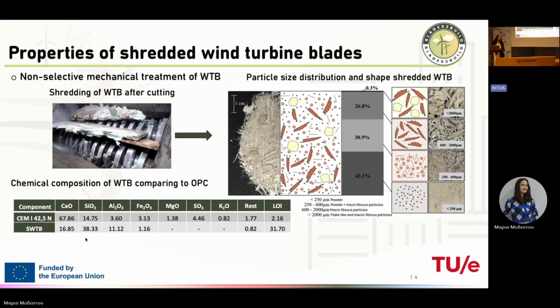By the way, it was not a part of this, but we also had some preliminary tests on other non-alkaline materials like gypsum. It's not really common, but it can also be used because gypsum has a neutral environment, so we don't have these problems. Here we didn't observe these problems, but I know that our colleagues made the test on virgin glass fiber, which has fewer epoxy contaminants, and they observed some alkali silica reaction, if it's not a cement environment but a direct alkaline, aggressive environment.